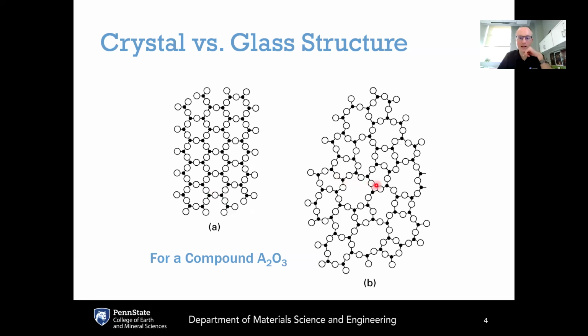Now, on the right-hand side, you can see that there is quite well-defined short-range order, that the basic structural unit here, this triangular unit, is the same on the right as it is on the left. The only slight difference is that there's maybe a bit more variation in the bond angle here between the oxygen, the cation A, and the next oxygen, where there's a bit more flexibility in some of that bond angle on the right, and that contributes a bit to the disorder of the glassy structure compared to the crystal structure.